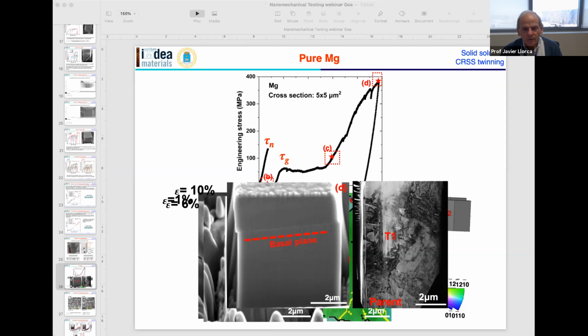But basically, when you go to higher, you can see here that you have a lot of plastic deformation due to pyramidal slip. So at the end of the day, with this test, you can measure from here the critical resolved shear stress for twin nucleation. And this here is the critical resolved shear stress for twin growth.